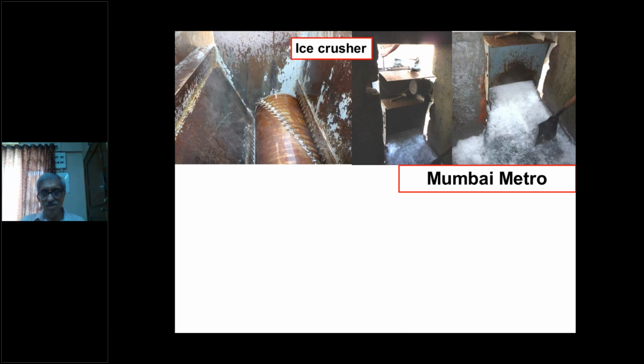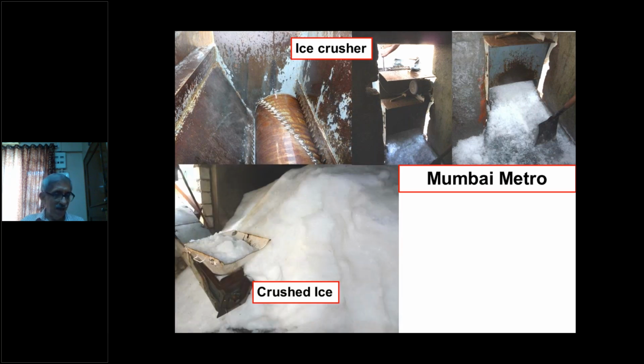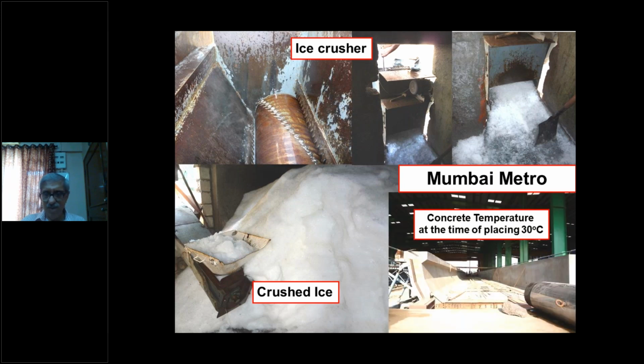Very small granules of ice flakes come out, which are collected, heaped and put on the conveyor and added as per the mix design of the quantity of flaked ice to be put. So this was done in Mumbai Metro. You can see the sections are not very large, but the specifications were as per the international standards. And the good thing they did was they ensured that all concreting was done at 30 degrees centigrade for all the precast members.